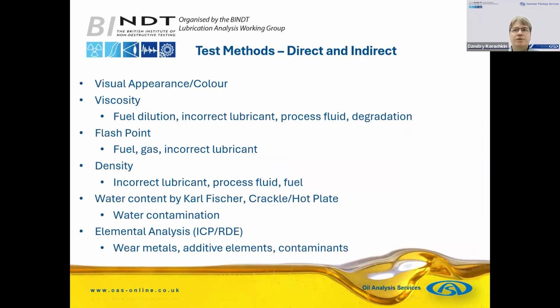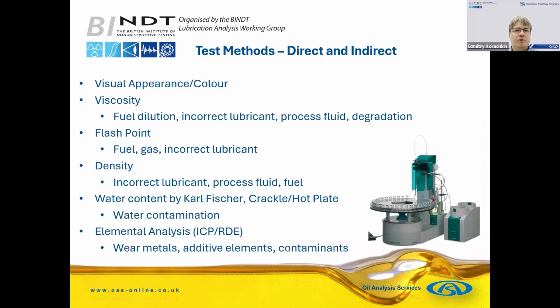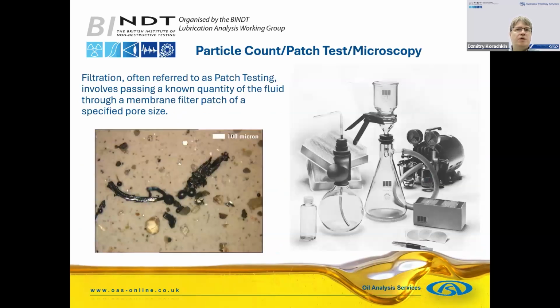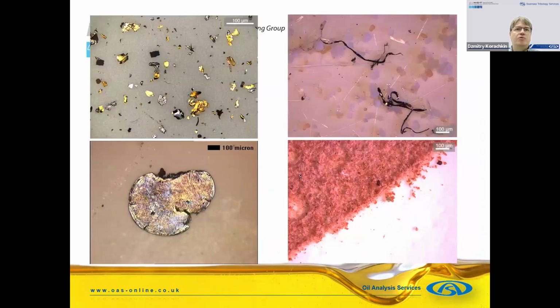And then elemental analysis using either ICP or a rotating disc electrode, looking for wear metals, additive elements, contaminants. Particle count may help detect ingress of particulates, but it's also useful to separate the more solid contaminants, or sometimes sludges, fibers, and so on, onto a filter membrane for further examination, either microscopic, and you're able to see quite a lot of difference between the different contaminants.